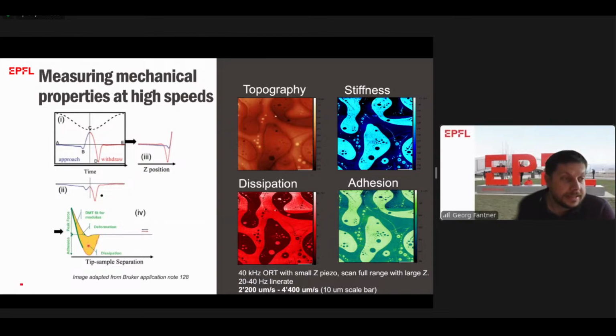So we can get stiffness from the slope, we can get adhesion, we can get energy dissipation, we can get stiffness of the whole sample. And so we get different kinds of images for each topography image. So we now really have a multi-parametric imaging method. And this again is something that you can commercially buy. It's something that you probably also have in your institute.